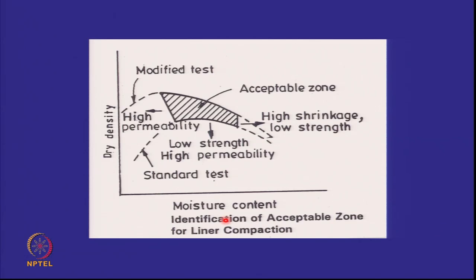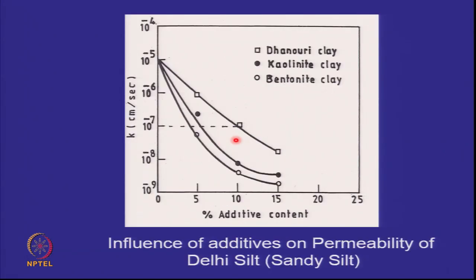And this we have already discussed earlier, we should preferably be on the wet side of the optimum. And here it shows that in Delhi silt, which was sandy silt, we added 3 types of additives: bentonite, kaolinite, and a local clay which comes from near Roorkee, it's called Dhanauri clay. So the round symbols show how the permeability decreased with bentonite, the dark symbols show how it decreased with kaolinite, and this shows how it decreased with Dhanauri clay.